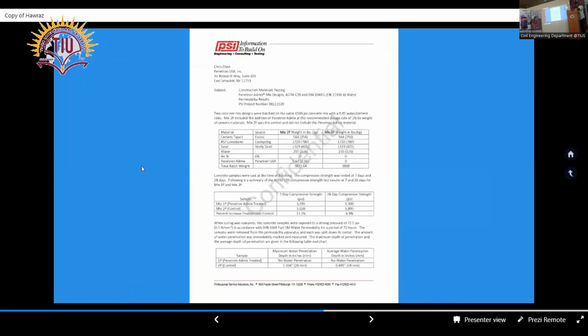Here's a test from an international laboratory from the USA. Maybe it's not very clear, but here we have the samples containing the Penetron admixture. There is no sign of water penetration. However, in the control sample with no additive, water has penetrated around 2 centimeters.